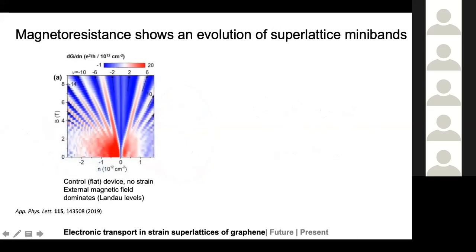I think we have time for the magnetoresistance. The magnetoresistance of flat graphene, which doesn't have any strain in it, shows this fan structure, which is called a Landau fan. Again, on the y-axis you have magnetic field, and on the x-axis you have carrier density. What you'll see is that as you increase the magnetic field, a different set of Landau levels open up, which result in these features in the conductance data. But all of them come together and meet at the Dirac point.